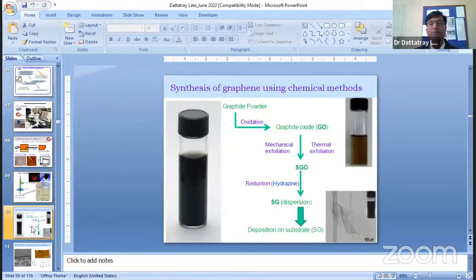Even very simple chemistry can be used, right? You take bulk graphite powder, you can do oxidation in the presence of strong acids such as H2SO4 or HNO3, and then you will get graphite oxide, right? Again, you do mechanical exfoliation by just ultrasonication, or you can do thermal exfoliation by heating the sample in a high-temperature furnace, and then of course you will get single-layer graphite oxide. Then you can reduce it with reducing agents such as hydrazine. You will get single-layer graphene, but this is of course in solution form.